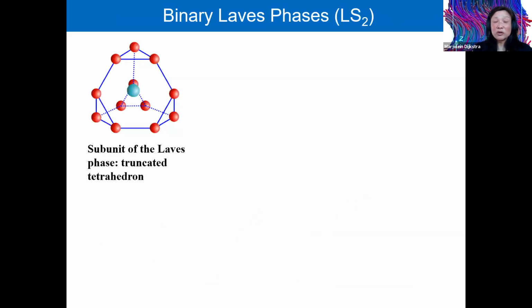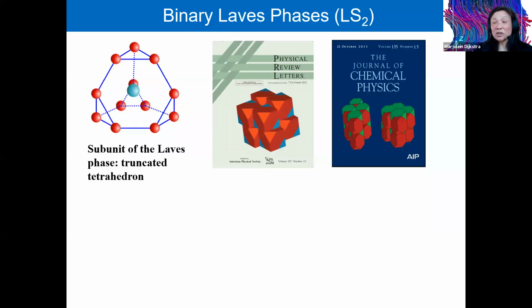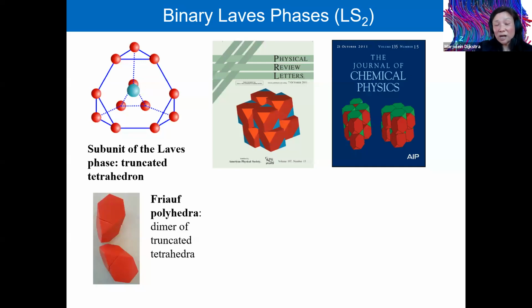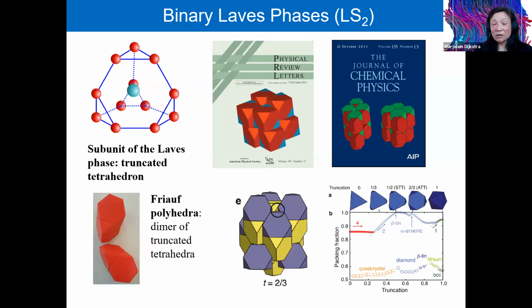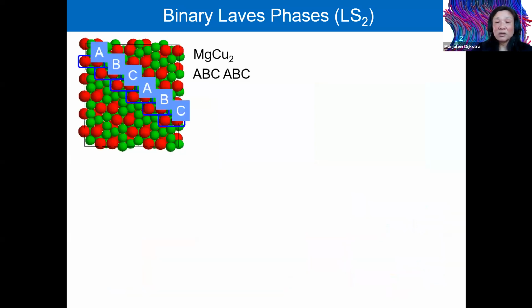So these subunits of the Laves phases, this is the truncated tetrahedron. One can immediately make these icosahedral clusters. These truncated tetrahedra also like to form dimer lattices. This was already shown on the covers of these two journals. And these dimers of truncated tetrahedra are also called the Friauf-Laves polyhedra. One can stack these Friauf-Laves polyhedra into a dimer lattice, which is basically a Bravais lattice.